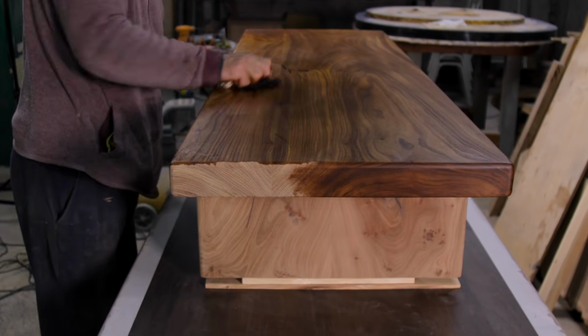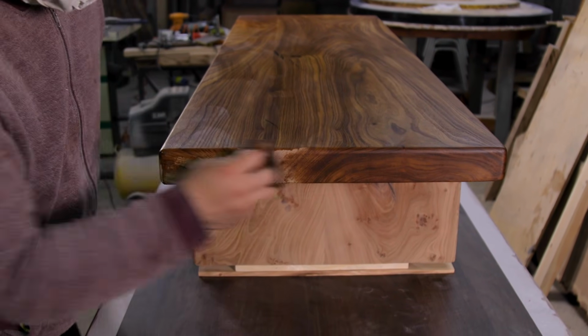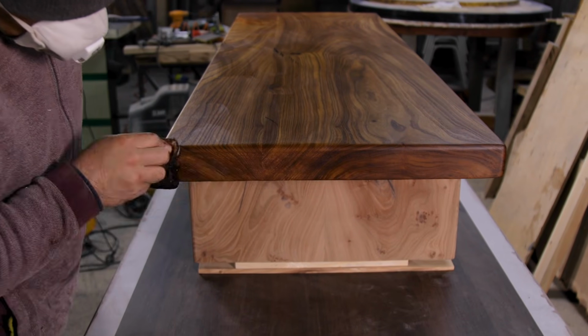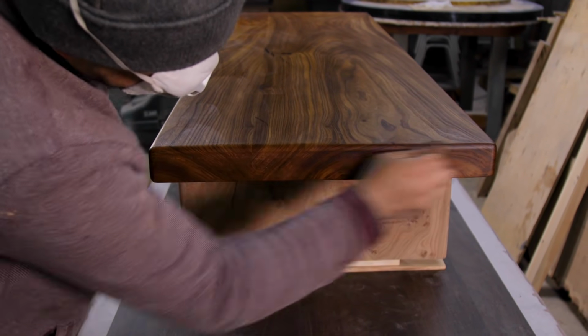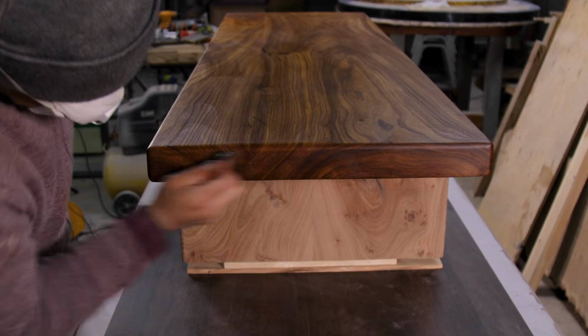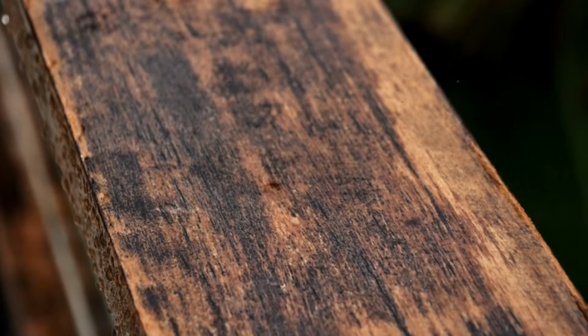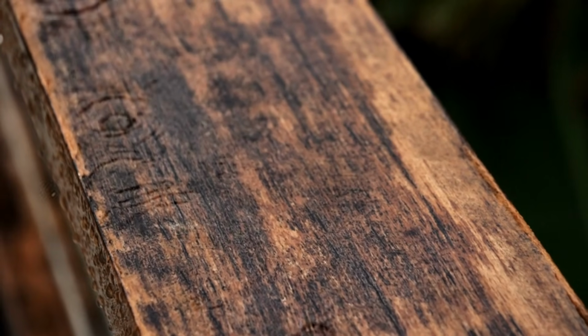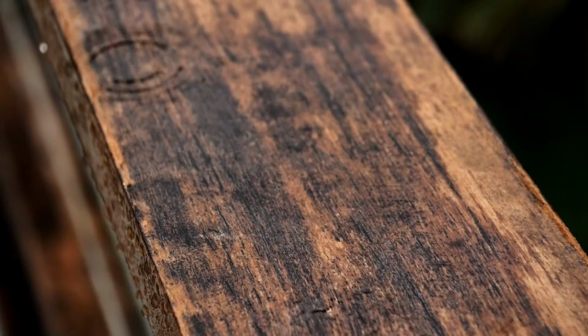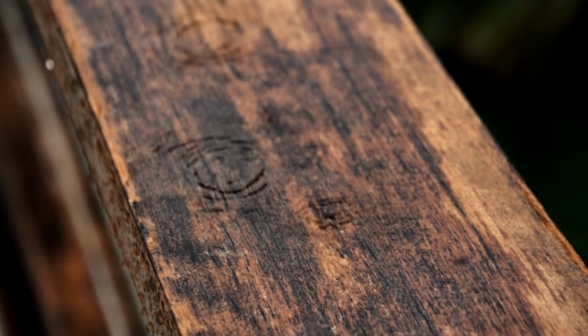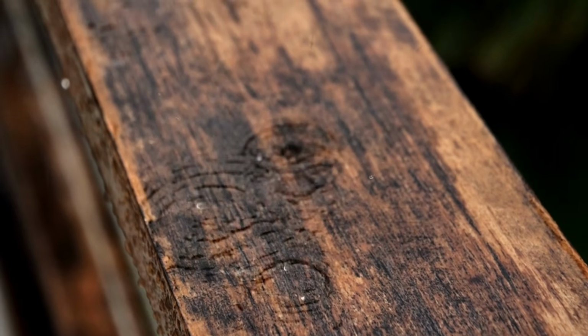In marine species, tyloses physically block water from traveling through the wood's vascular system. And here's something that surprised me. In some marine applications, coatings can actually make things worse. If moisture finds its way behind a coating through an end grain check or a fastener hole, the coating traps it against the wood. Now you've got sustained moisture with no way to dry, which is exactly what decay organisms need. The shipwrights understood that a naturally durable species with no coating can wet and dry freely, and the wood's own chemistry handles the rest.